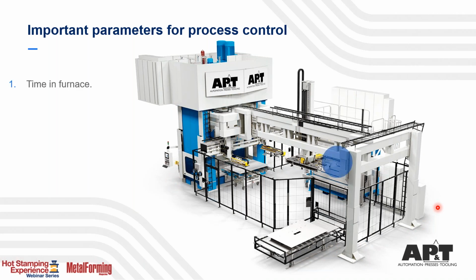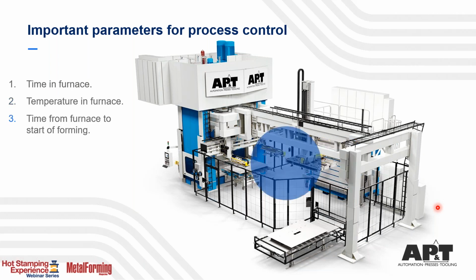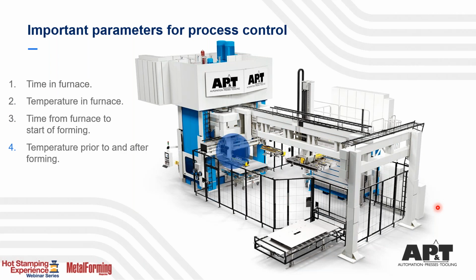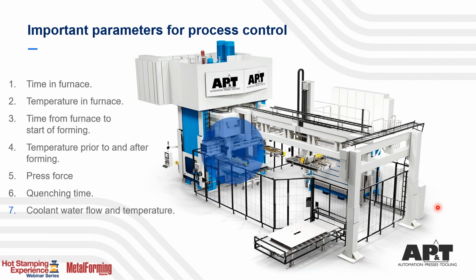First parameter we need to monitor is time in furnace. Secondly, the temperature in the furnace. So we all heard these influencing parameters in the first part of my presentation. Now you see that you need to monitor them as well. Then the time in air from furnace to the start of forming needs to be monitored. Temperature prior to and after the forming. Press force, quenching time, the cooling water flow and the cooling water temperature. Hotspot detection after quenching.